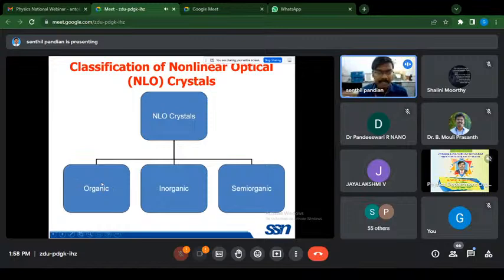The problem with organic single crystals grown by the SR method is that the SHG efficiency of these organic single crystals is very high compared to the standard KDP, potassium dihydrogen phosphate single crystal. But the problem with organic single crystals is that, due to weak van der Waals forces, we cannot grow large size single crystals.